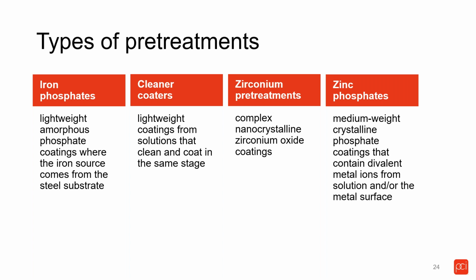From a corrosion perspective, zirconium is close to zinc phosphate, but not quite as good, depending on the spec. With most customer specs, it will be able to match zinc phosphate, but if you have a really challenging spec, zinc phosphate will probably still outperform it a little, though they're still very close. With that being said, your best corrosion protection from a pretreatment perspective is a zinc phosphate with a sealer. Zinc phosphate lines usually have 6 or more stages, so they require a lot of square footage to run.